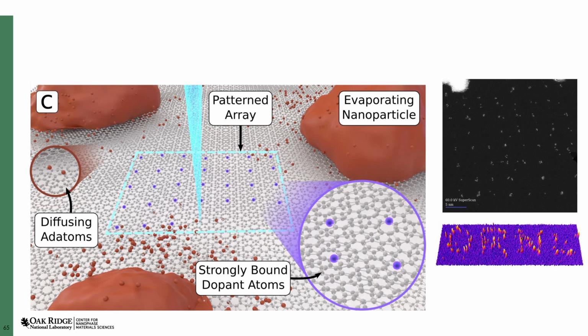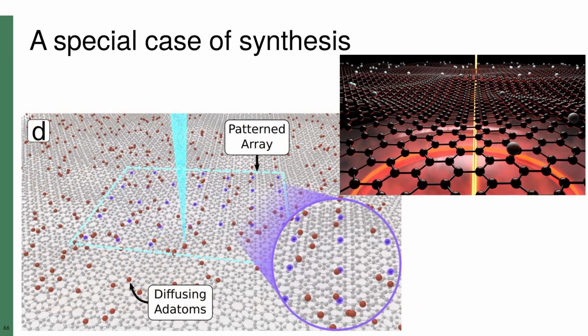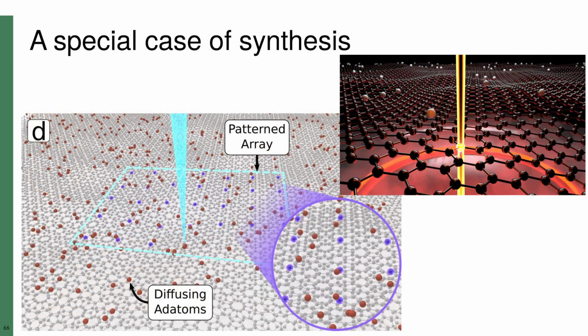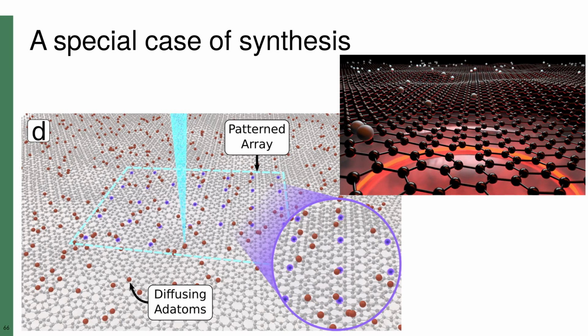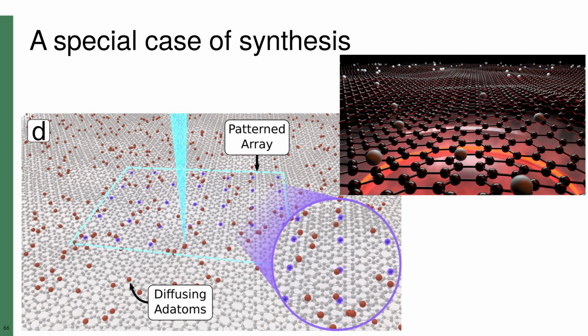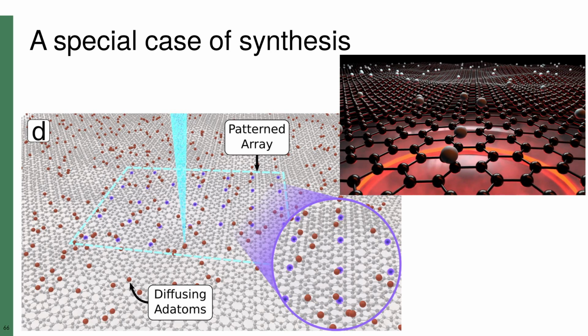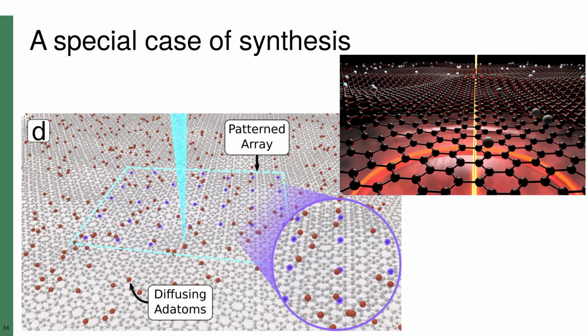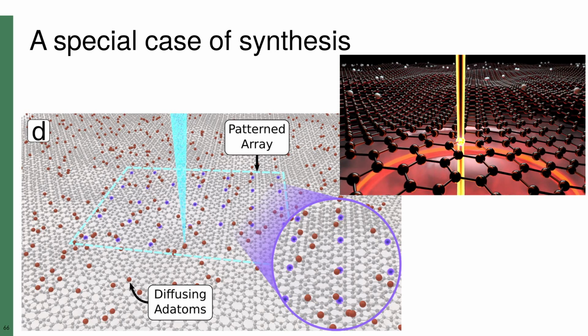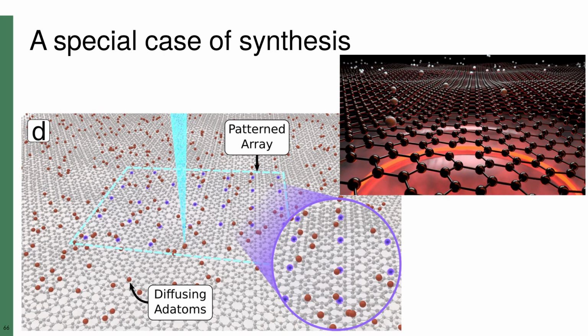In this picture, however, we still have source material sitting on the graphene surface. We would really like this to be located somewhere else, both because it cleans up the graphene and because we would then have independent control over the temperature of the graphene substrate as well as the source evaporation temperature. Our ideal picture then looks something like this. We have a perfectly clean graphene substrate. Atoms of our choice are evaporated from a separately controlled source onto the surface where they can continuously diffuse around. Only when our beam comes down and makes a modification do we obtain the result we want.